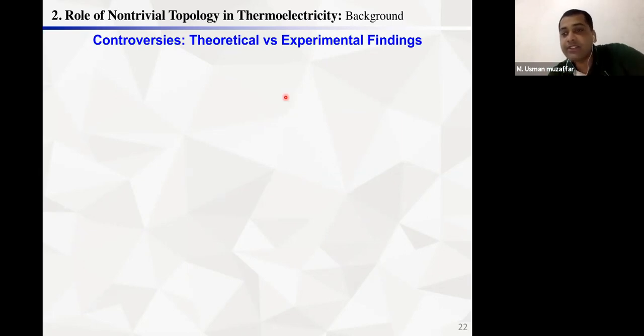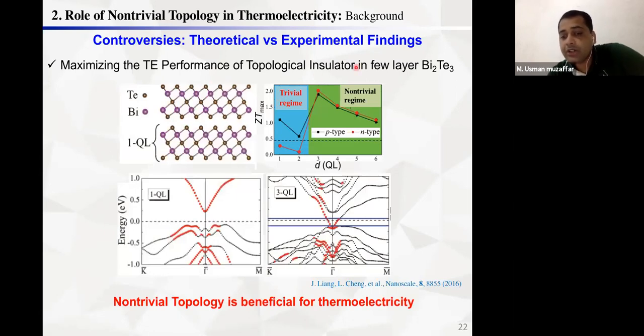But in this context, we have conflicting findings between theory and experiment. Here is an example of a theory which supports that non-trivial topology is beneficial for thermoelectricity. They consider Bi2Te3 as a prototypical example, and this Bi2Te3 has a layered structure which consists of quintuple layers. One quintuple layer has five layers of Bi and Te, and in this paper, the authors reported that the one quintuple layer is topologically trivial. It's not a topological insulator, because it has a fundamental band gap.